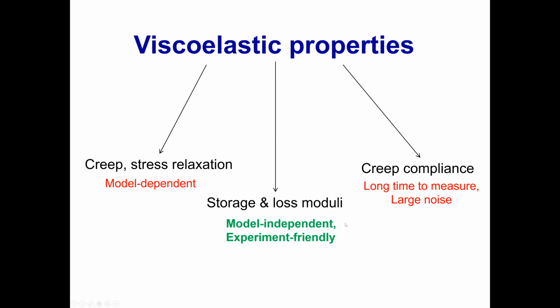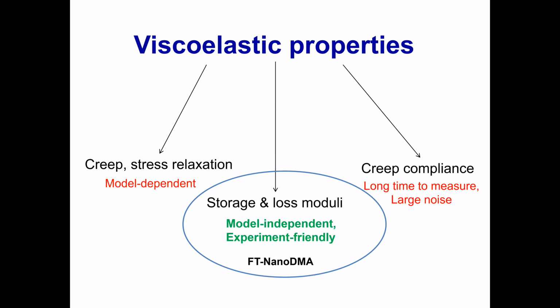Creep compliance is long time to measure and pretty large noise. So there are literally only a few papers devoted to that. And this method is like, why bother? It's more laborious and it's not giving you good information as others. So we choose storage and loss modulus measurements. And this is what is called dynamical mechanical analysis, or DMA.